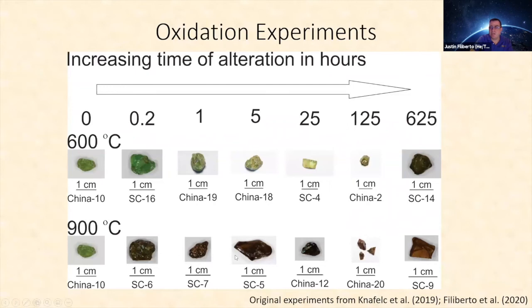So we're getting a darkening. And then after about a day into about a couple of weeks, we start to see a change from olivine to darkening to a reddish color, and a much duller red coating forming after a month. So you can see that there's a change in mineralogy with our coating happening through time, where we're producing one mineral and then producing another. And this is the formation of iron oxides. We're first forming magnetite on the surface after a month at 600, and we're forming hematite as we go to longer and longer times of oxidation.